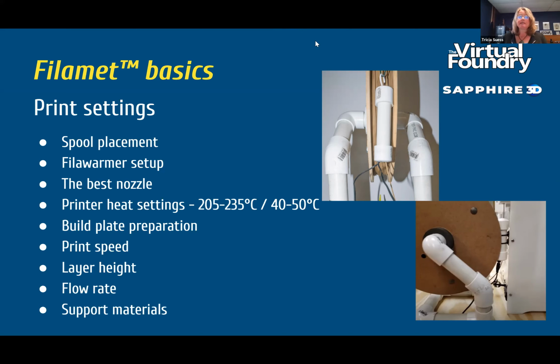Now, your print heat settings. Some people think that you're actually going to try to melt the metal as you're printing it, and they think they need to have a really hot printer. That's not the case. The only thing that you're melting during printing is the plastic. So your printer nozzle only needs to get as hot as it needs to melt the plastic. So that's going to be a range of 205 to 235 C. Your print bed will be at a range of 40 to 50 C.